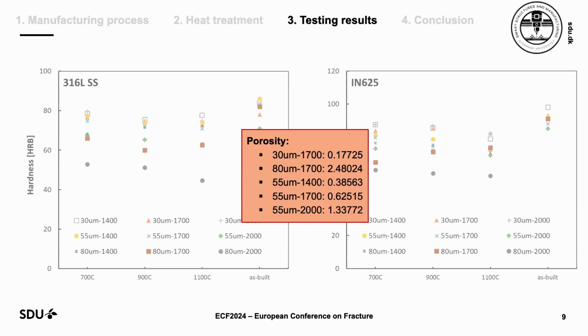Another factor, generally speaking, is the porosity level as well. So when we talk about different process parameters, for example, layer thickness or the scanning speed, we can see, for example, when we increase only the layer thickness while keeping the scanning speed, the porosity level increases. This is just before the heat treatment. And that's one of the main issues, porosity, when it comes to additive manufacturing. And we know that the porosity is there. Of course, with advancement in technology, the new machines are arriving and the level of porosity gets smaller and smaller, but it doesn't mean that we don't have any porosity. Based on my knowledge, there is no machine producing a part with zero, or even almost zero, porosity.